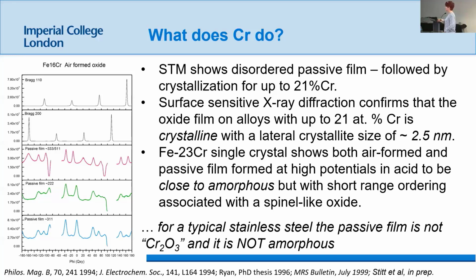So here's the takeaway message that's really important. The passive film is not Cr2O3, so if that's what you're modeling, you're wrong, right? At least under air-formed or high-potential conditions, it's much more likely to be a spinel than a corundum, and it's absolutely not amorphous.